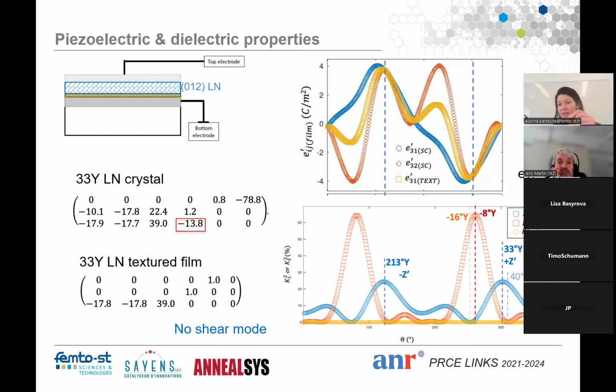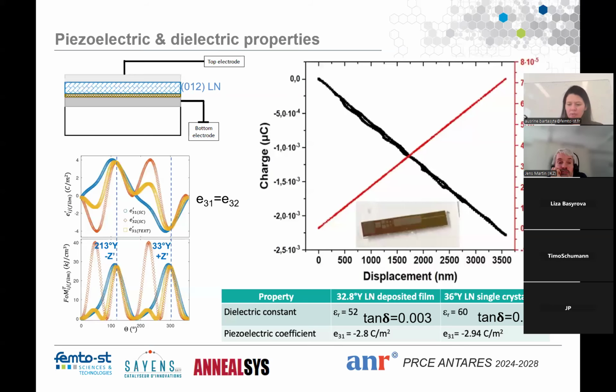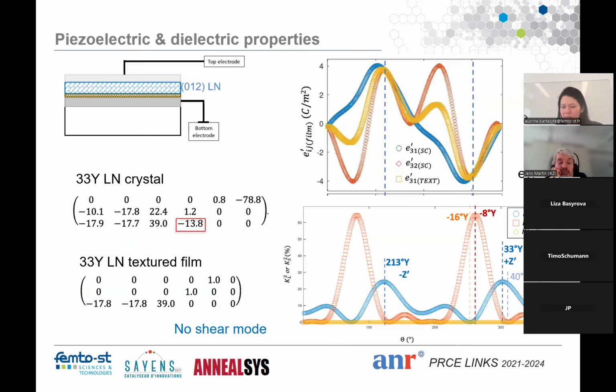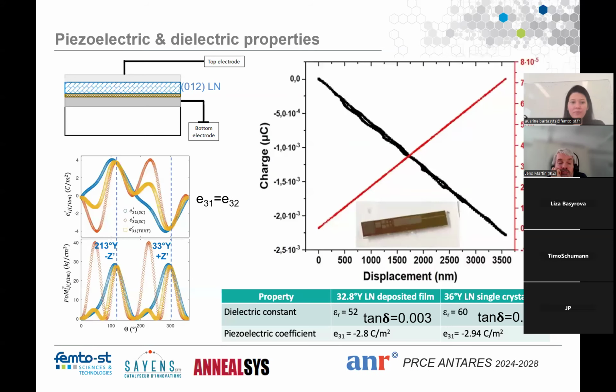So basically, the preference would be Y36, a few degrees off, where the shear wave coupling becomes zero. Okay, like this, you do not excite the shear wave and you get pure longitudinal. But in the textured film, this coefficient is zero. So basically, you never excite this shear wave in Y33 oriented films.